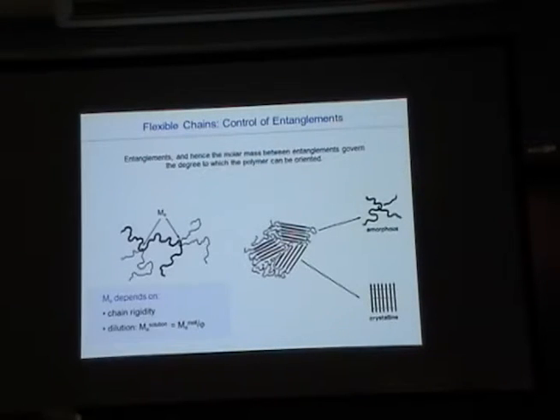Why is this important? The amount of knots will determine the microstructure. It will determine what we call here the lamellar crystal thickness. If you have many, many knots, many, many entanglements, the material stays amorphous. Or, if you play a trick and get essentially rid of all the entanglements, you get essentially a single crystal of materials. The entanglements also tell you why actually polymers are often very easy to process.